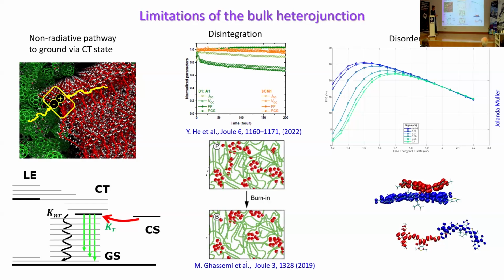And then, of course, we have the fact that the arrangement of our donor and acceptor molecules next to the interface is probably going to be very important in controlling the energy of this state. And yet it's not that well controlled. So we may have different arrangements of our donor and acceptor next to the interface, and they may present different energies, and that would introduce disorder. And so I used the model I introduced earlier, actually Yolanda did it, to look at the effect of increasing the disorder in the energy of the interfacial state, and we can see that it compromises efficiency, so we would like to reduce it.